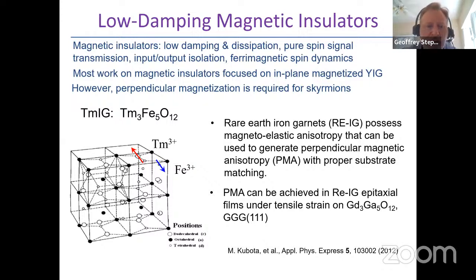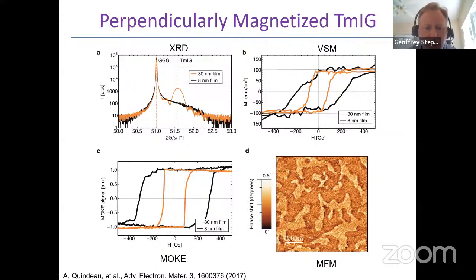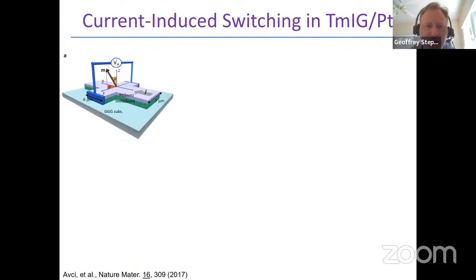And so we've been very interested in these kinds of materials, which again are multi-sublattice ferrimagnets that can be tuned to have many of the same dynamics as I've shown you for the metals, but other properties that you can't achieve with metals that we think could be quite interesting. And so the growth of a whole palette of these materials has really been perfected by Professor Ross's team to get perpendicular anisotropy, to control the magnitude of the anisotropy, for thick films down to very thin films, down to films on the order of a couple of unit cells.